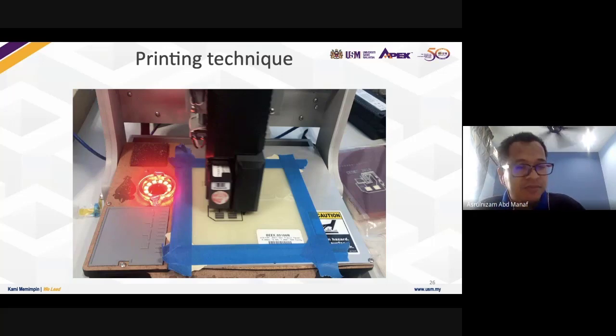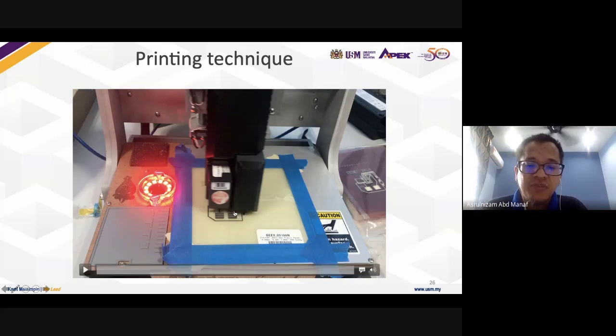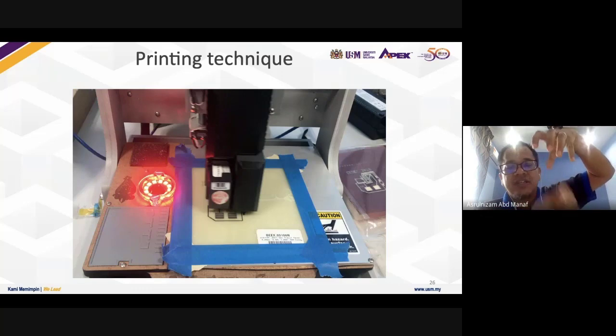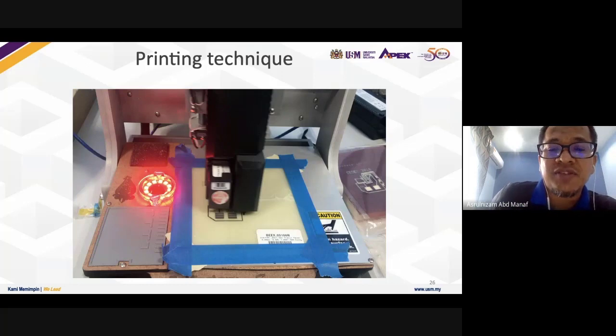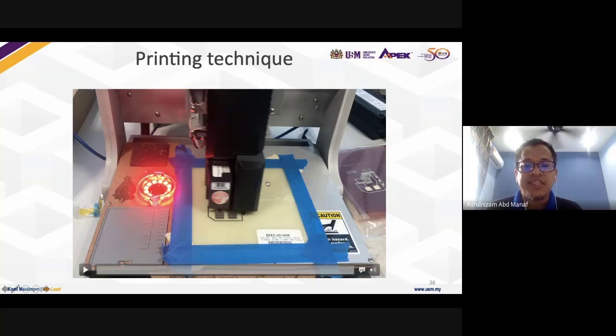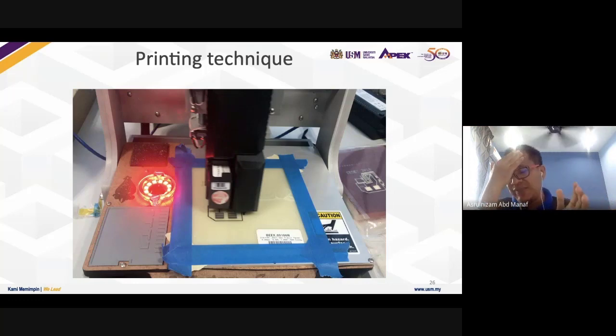When you have a polymer that must be conductive, you have to add particles, the silver flake. Because of that, we have to tailor-make in terms of the nozzles because the particles can clog the nozzle. That is the first problem we face. So how did we do it in my lab? We bought a lot of empty cartridges, and in this cartridge they have a sponge. So we have to learn the mechanism of the cartridge sponge.